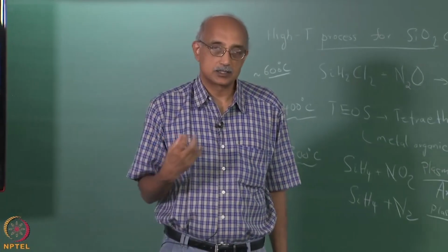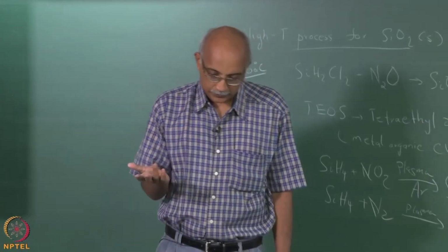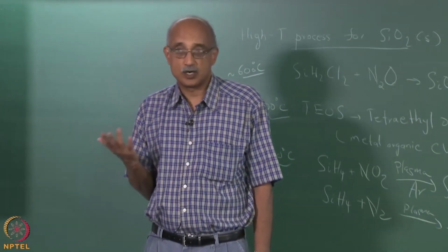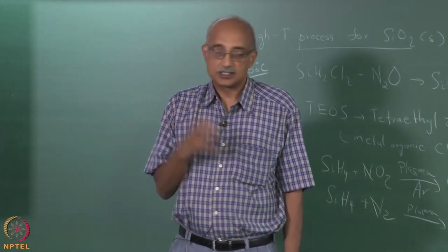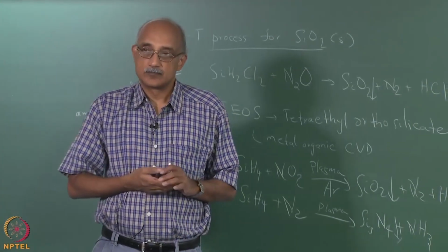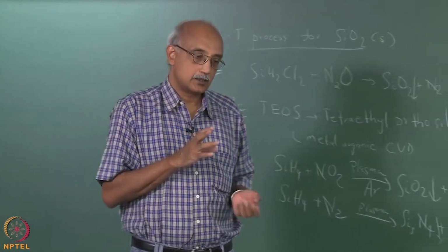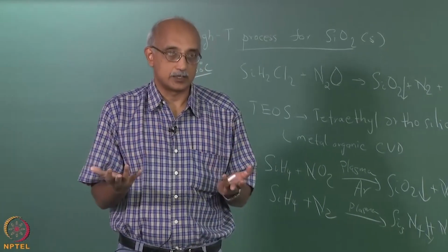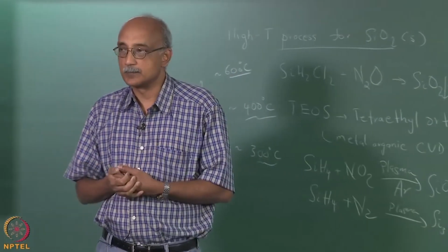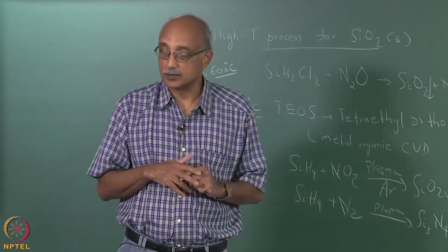So, it actually starts attracting moisture, which then reacts with the boron and you start forming boric acid. And similarly, in the case of the phosphorus additive, if you do not control the amount of phosphorus properly, then essentially it can start acidifying and start forming H3PO4, and both of these are obviously not desirable.